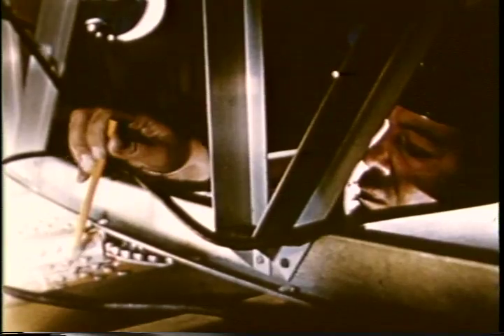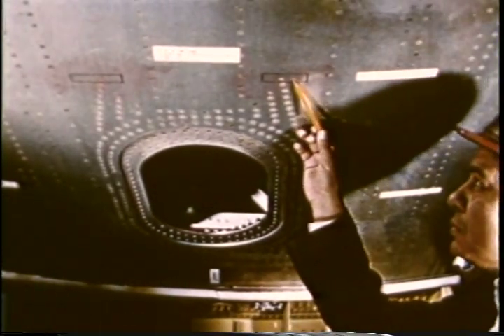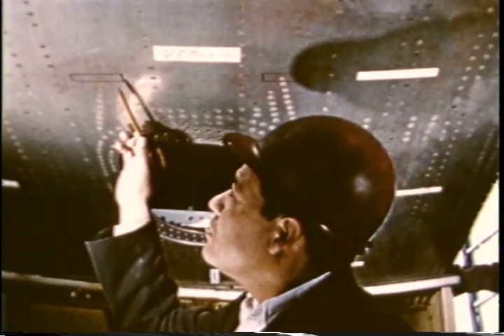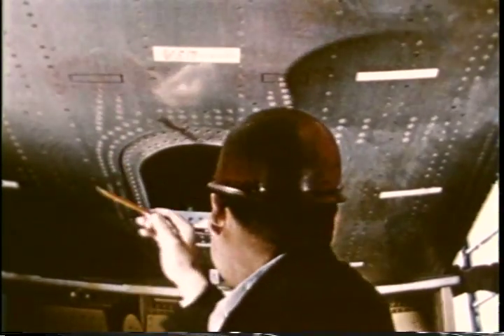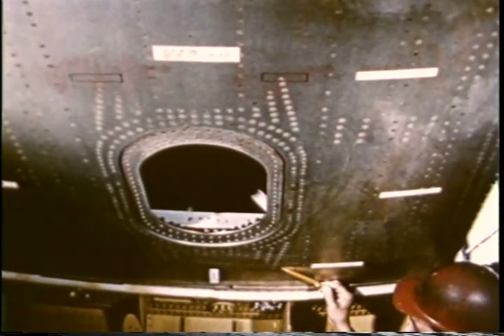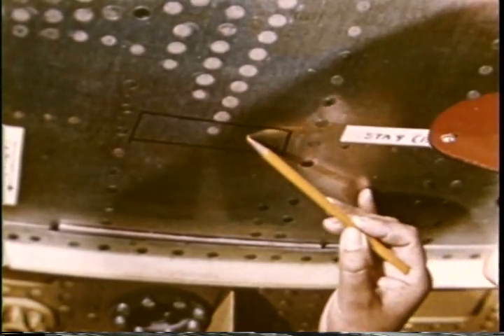Only after 180,000 cycles were fatigue cracks found. Suspicious areas were then checked with dye penetrant by spraying the dye over the surface and allowing it to penetrate. The excess was then wiped off and developer was sprayed over the area. The red dye leached into the developer where cracks were present. Other fatigue cracks were found and evaluated. Cracks appeared at the corners of the access door reinforcement doubler and were propagated through the lower surface skin, emanating from the end rivet.